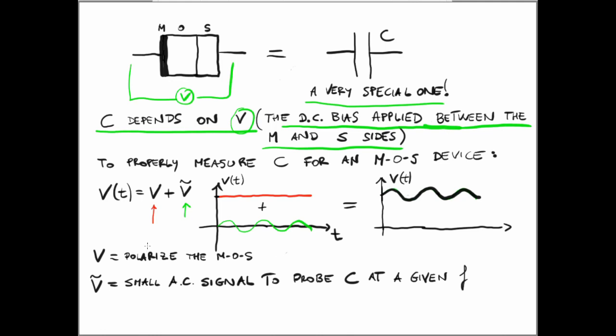By recalling what we said just a moment ago, in general, to measure the capacitance of a device, I need to apply an alternating signal with a certain frequency. And together with the fact that in an MOS device, I need to polarize my MOS device properly in one region or another, accumulation, depletion, or inversion, and this will influence the capacitance that I get. This means that in the case of MOS devices, to properly measure the capacitance, I need to use a very special signal, a voltage V that is a function of t, made by the superposition of a DC signal plus an AC signal.